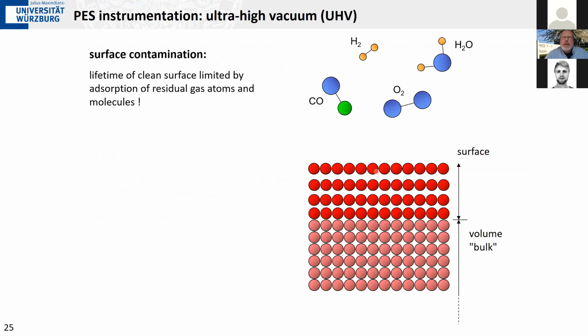When we have a material, the surface will always be the interface to the vacuum, and what we call vacuum is not really a vacuum. It's not empty. There will be a certain density of gas. It may be a low density, but it is nonetheless a density of residual gas atoms and molecules, and they can eventually, when they hit the surface, stick to the surface and then give rise to the growth of such an adsorbate layer that I just depicted previously.